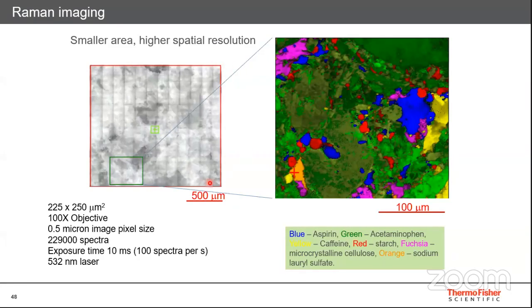So here they have used Raman imaging, because of which around 2,29,000 spectra were taken in a very short time, and you can do the analysis of your sample in a very short time. So it has a very high spatial resolution. A very small sample area, around 5 micron, for around 100 microns. Sorry, 225 by 250 micron have been analyzed in a very short period of time.